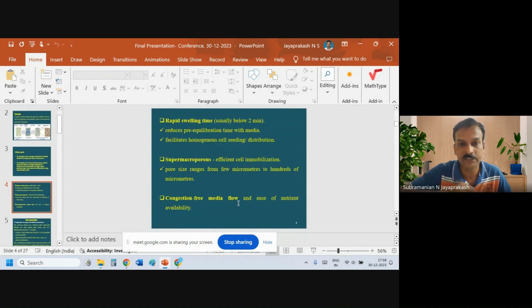So if you see the advantages of these cryogel materials, the first advantage is a rapid swelling time, usually below 2 minutes. This will reduce the pre-equilibration time with the media, and also facilitate homogeneous cell seeding and distribution. Another advantage is that it is super macroporous, which will aid in efficient cell immobilization. The pore size ranges from a few micrometers to hundreds of micrometers. It will also give congestion-free media flow, and ease of nutrient availability for the growing cells.